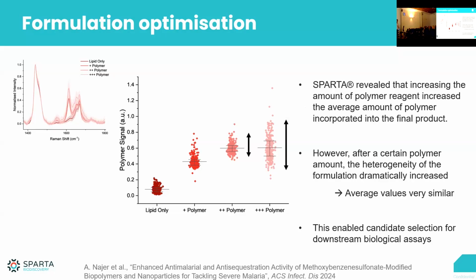And what's crucial here, and this looks a bit familiar maybe from the targeting ligands plot that I've showed you, and we've seen this quite a lot, is that you can push it to a certain amount, and then you get relatively little gain in the mean, but you can see that the variation between these particles becomes huge. And this is really what we saw here with this excessive amount of polymer as well.